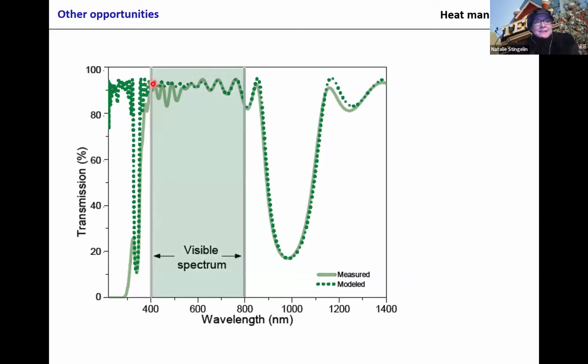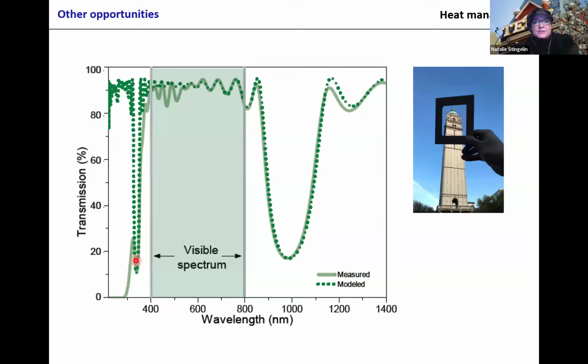Here you see nicely we have very high transmission in the visible, but we do reflect in the near infrared. You also see that the quality of the mirrors is very good. How can you see that? You always see in my graphs the solid line, which are the experiments, then the dotted line, which you can simulate using a methodology called transfer matrix methodology. The fact that our mirrors can be so well modeled means we really have high quality mirrors.